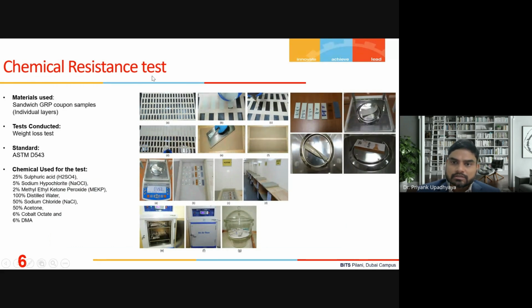You can see in these pictures right here. This is the process for individual layers. I have discussed those 6 layers. So for each layer, we are making compression molding specimens, which are looking of, let's say, this nature. The dimensions are 1 inch by 3 inch. And what we do after this is that we put them in desiccators before we start the experiment for 3 hours, so that the moisture and everything is cleaned out. Then we start doing the weight loss experiments.